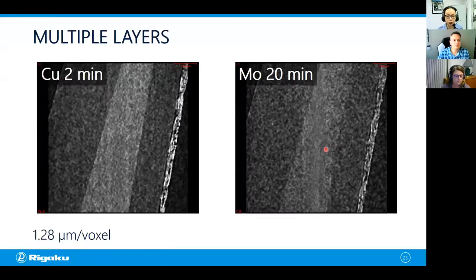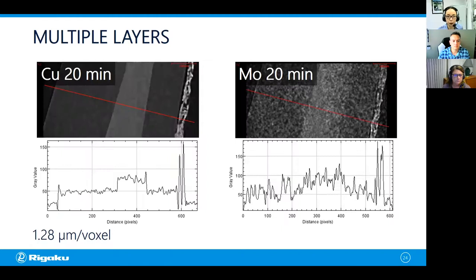And even after 20 minutes, you can barely see that the center UV resin part is higher density than the other two sheets. So you can, you know, right off the bat, see that the molybdenum is probably not a good choice for this sample. Now, just to do an apples-to-apples comparison, I did a 20-minute copper scan as well. And this is the result. If you spend 20 minutes with the copper, you can clearly see that this is UV resin and you have two different polymer layers and paper.